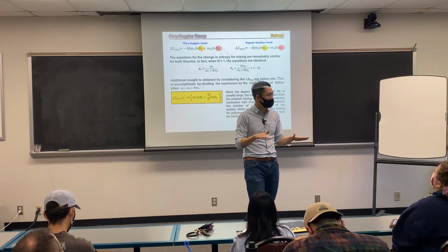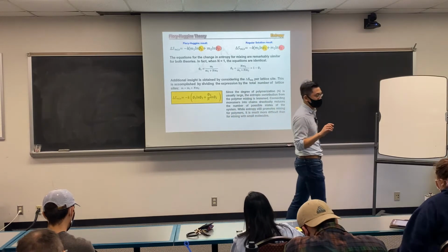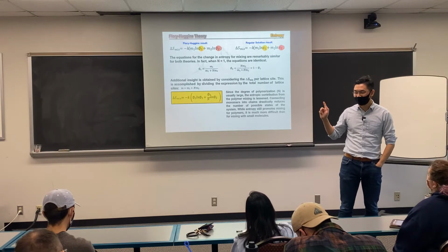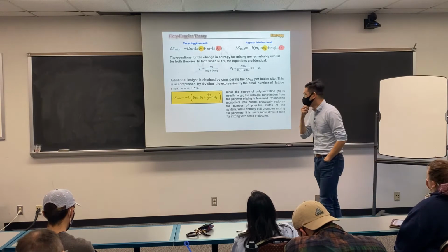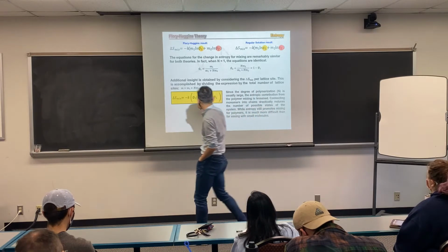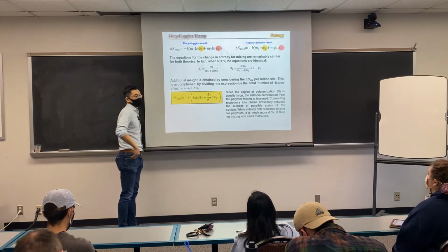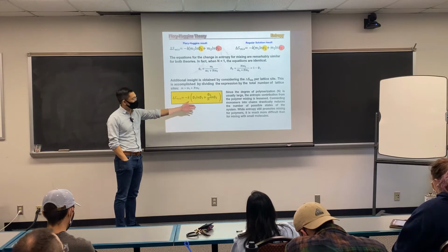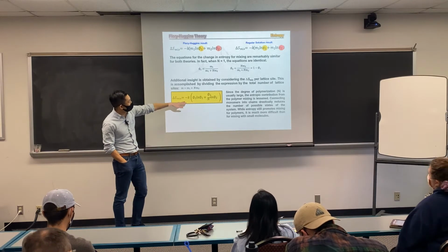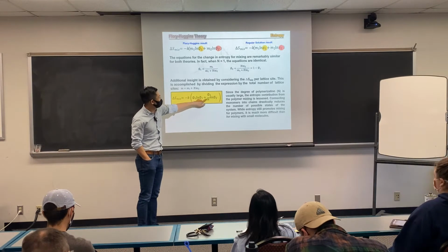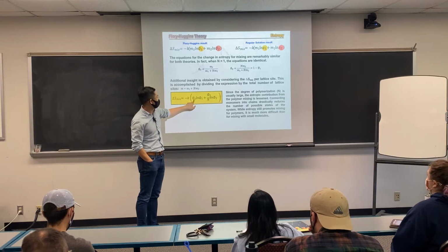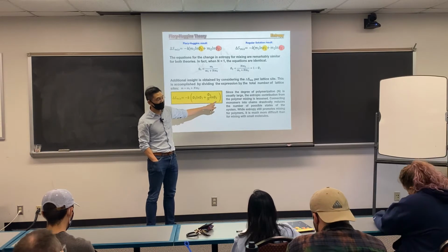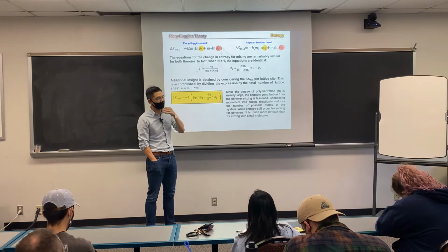I would like to slow down here a little bit. Let me emphasize one more time. Your polymer doesn't contribute a lot, okay? So a natural extension of this for a polymer-polymer mixture will be easy to understand. You can apply the same theory and argument: if you consider polymer 1 and polymer 2, this will be phi 1 divided by n1 and phi 2 divided by n2. n1 and n2 are the degrees of polymerization for both polymers.